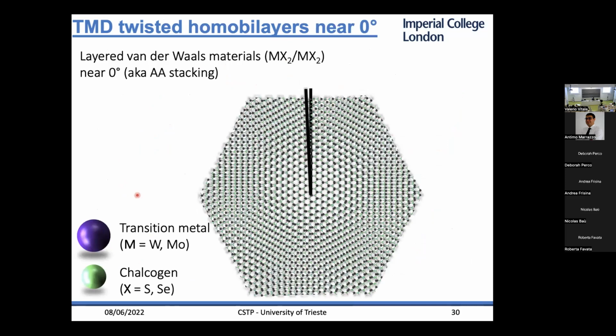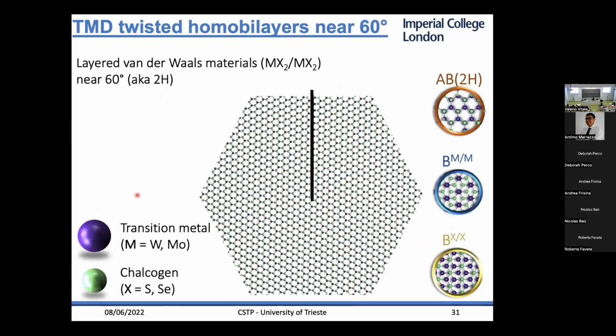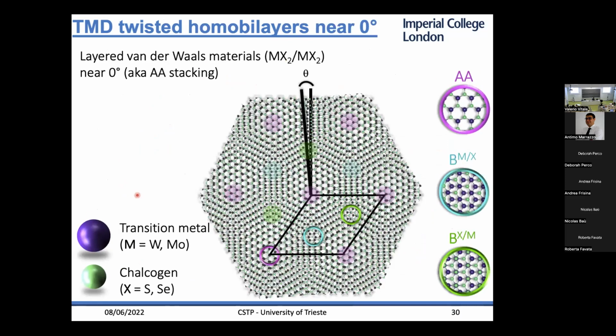Right, so you can play the same game as we played for graphene, for example, and then you generate these Moiré patterns. And these Moiré patterns will contain, if you start from AA, for example, as I'll show you, regions of AA stacking and regions of Bernal-like stacking, as well as other regions where you have a continuum basically of stacking between these two.